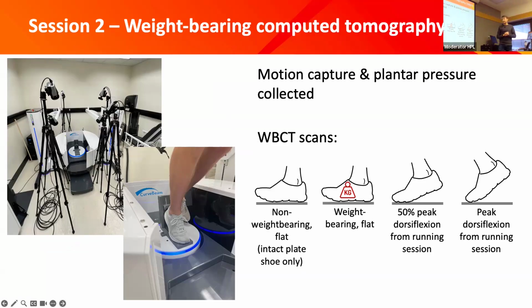And then we had people stand in a bunch of different postures. So we had them stand in the non-weight bearing posture to mimic what would happen in the clinical CT setting. We had them stand in a full weight bearing flat posture. So all the weight was on the right foot and their left foot was just kind of in the air. We had them stand at a 50% peak dorsiflexion posture, and that was estimated from the running session. So we took half their peak dorsiflexion from that running session, made them stand in it in this session, and then peak dorsiflexion also from that running session. And we did this for both shoes.